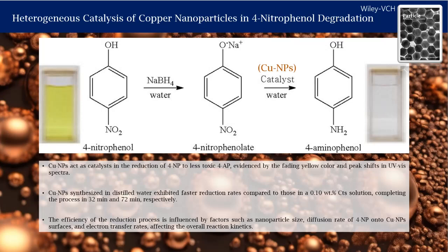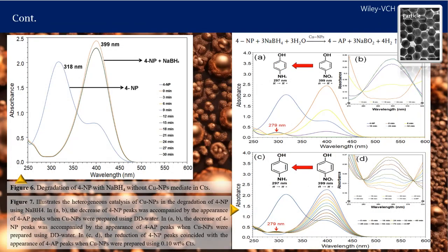Heterogeneous catalysis of copper nanoparticles in 4-nitrophenol degradation showed that copper nanoparticles catalyze the reduction of 4-nitrophenol to less toxic 4-aminophenol, as indicated by color fading and UV-visible peak shifts. Synthesized in distilled water, copper nanoparticles exhibit faster reduction rates than in 0.10% chitosan solution, completing the process in 32 minutes and 72 minutes, respectively.